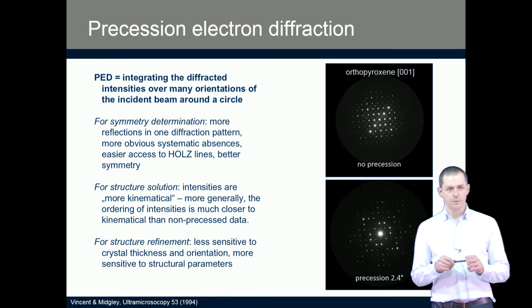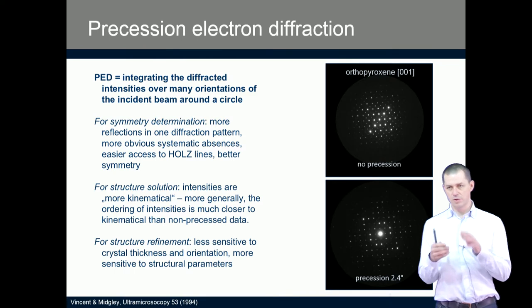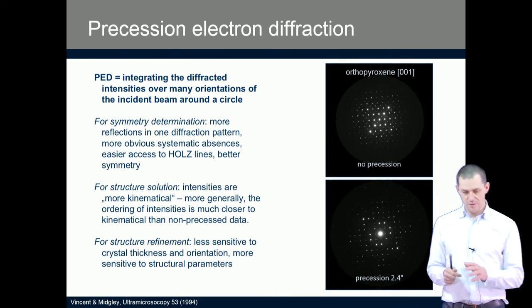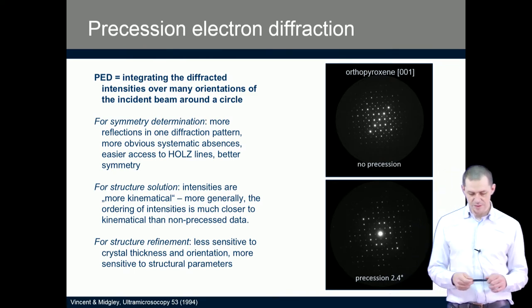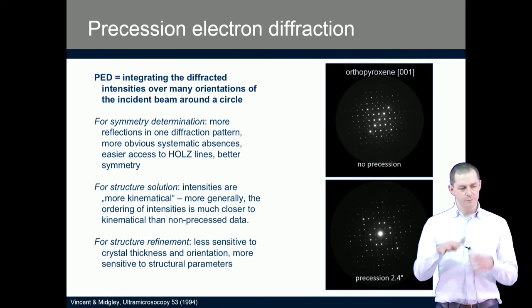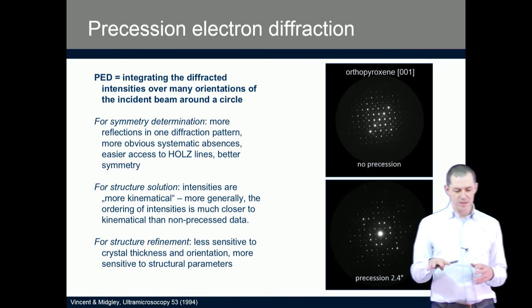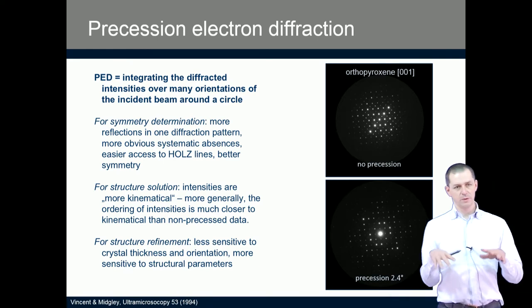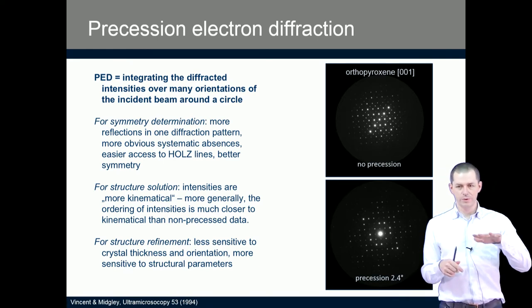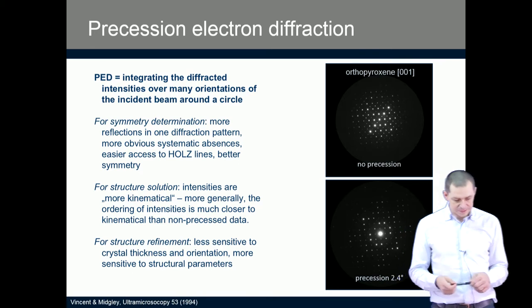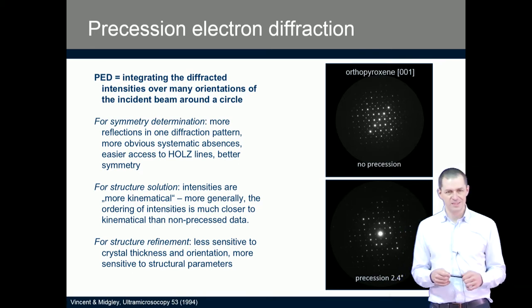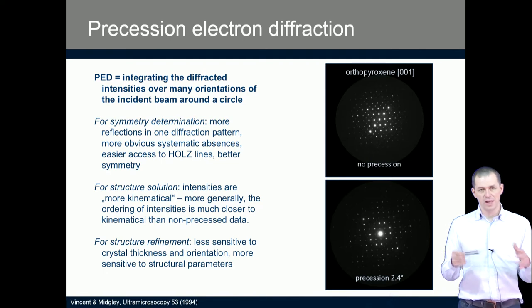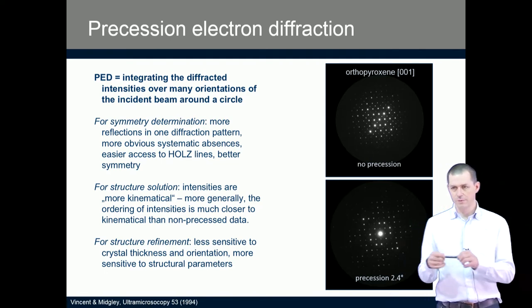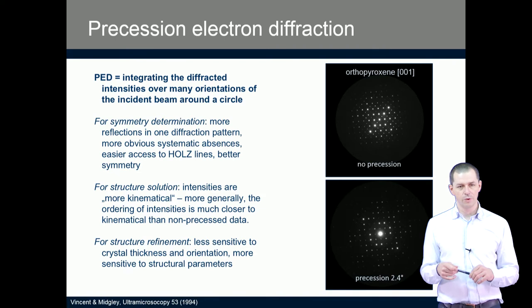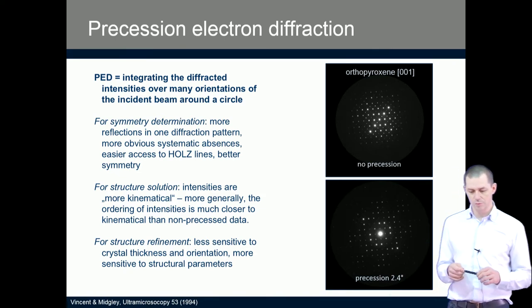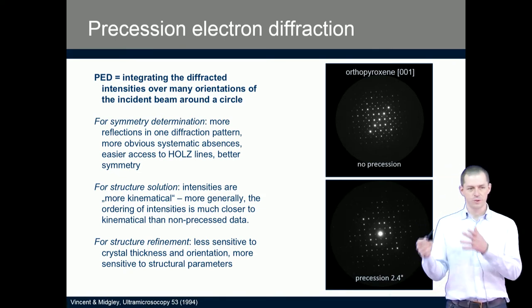For example, for symmetry determination, if you want to determine the symmetry from the oriented diffraction patterns, then the PED, precession electron diffraction, images look more symmetric because they are not so sensitive to the exact orientation of the crystal in the beam. For structure solution, intensities are more kinematical, or less affected by dynamical effects, and therefore they are more easily handled by structure solution software like Superflip, SHELXT or SIR.